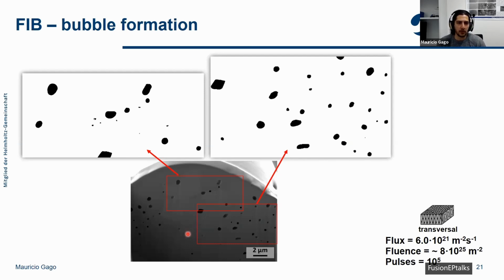In these samples, we can already see that the amount of bubbles on the surface is very significant. Actually, analyzing this image, for example, we see that the bubbles occupy 3% of the analyzed area. And how this affects the material behavior is still not completely clear, but if we have more pores, then this will at least affect the heat dissipation. And this is already very important because then the surface will always be warmer than expected.